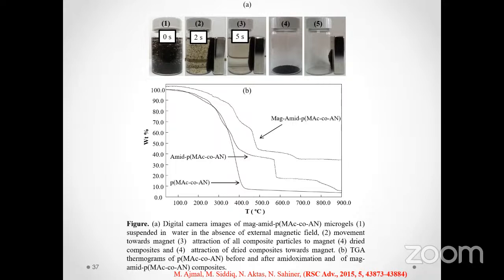Now, what is the advantage of this magnetic field? I will discuss it in the next slide. Here, I will talk about this thermal stability, that this system was also observed to be thermally stable below 200 degrees centigrade. And it was concluded from this observation that this system can be used at industrial scale for the treatment of contaminated water below 200 degrees centigrade.